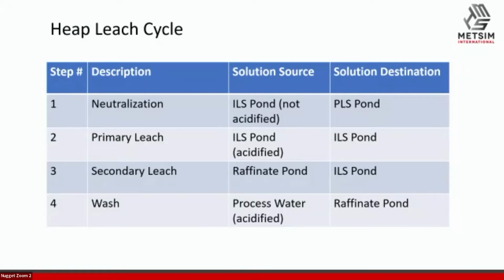Step 1, let's neutralize. So we take the fresh ore after it's stacked and take the most mature solution out of the ILS pond and leach with that. That would be non-acidified. Purpose of leach step number 1 is, as the name denotes, neutralization. We're looking to remove all the acid if possible. And if we're lucky, we'll even precipitate a little bit of iron if we get that acid down low enough. Lower acid, lower iron, less lime downstream. So it's a win-win there.